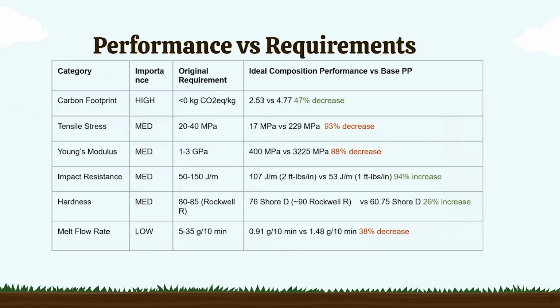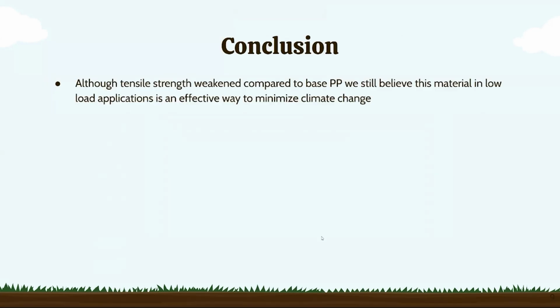Looking at a conclusion of our data, we were able to get a 47% decrease in our carbon footprint compared to base polypropylene, which was our overall goal. And although our tensile and Young's modulus did decrease by a significant amount, we also saw increases in our impact resistance and hardness. In conclusion, although tensile strength weakened compared to base polypropylene, we still believe this material in low load applications is an effective way to minimize climate change.